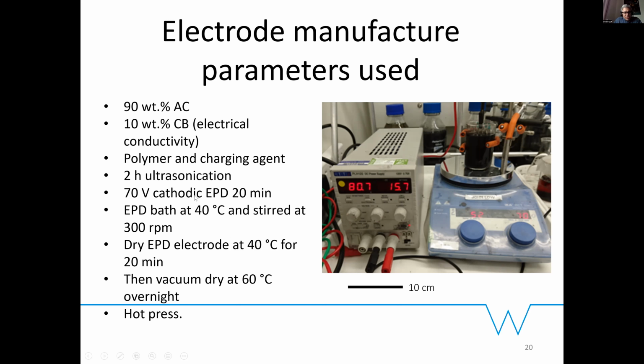The timing and the voltage were selected after meticulous amounts of research to get the best deposition of the activated carbon on the aluminum foil. And also we had to keep the bath stirred at this stirring rate and kept at a temperature of 40 degrees C. Then of course we did vacuum drying and so on, and in some cases we compared with hot pressing and without hot pressing, and the results will be shown in the coming slides.